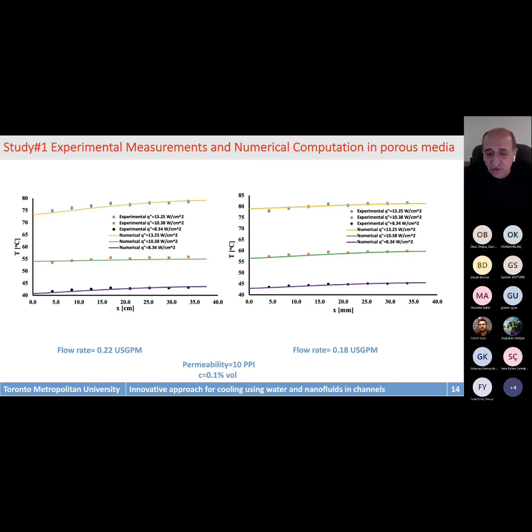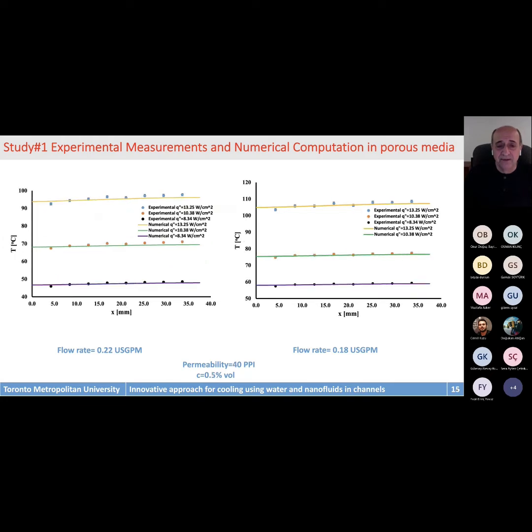Then we also changed the flow rate. We increased it to 0.18 and 0.22 US gallon per minute. And we notice as the flow rate increases, or as Reynolds number increases, then we start having differences between experimental and numerical, because at 0.3 US gallon per minute, we are in the transition zone between laminar and turbulent flow, and our model, we are keeping it in the laminar regime, so we start finding differences if we go above 0.3 US gallon per minute.